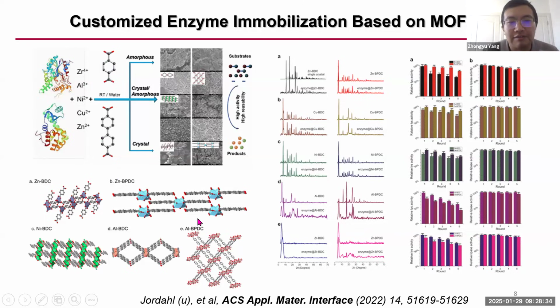And we found that some of the MOFs can form crystals. Some are multi-phase crystals, and some are completely amorphous. And that's perfect for my goal, right? So we load a couple of different enzymes and we check the reusability. The enzymes on most of the 10 MOFs are highly reusable, which is good. That means the enzymes are trapped inside. And crystallization was not significantly changed upon enzyme binding.